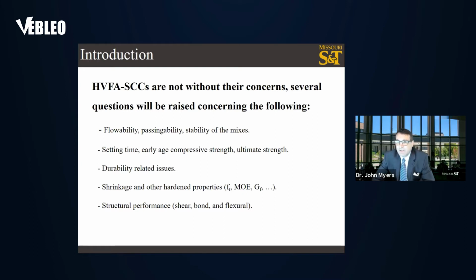There's a reduction in the coarse aggregate size and also amount, and the proportions combined with an increase in paste content can lead to increased creep and shrinkage of the concrete, decreased bond strength, and an interface shear transfer contribution to the concrete shear strength. This leads to additional concerns when incorporating high contents of fly ash. And these are part of the reasons why ACI had never allowed high usage of high volume fly ash in the past.